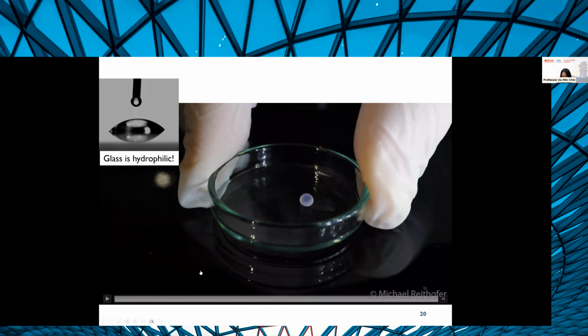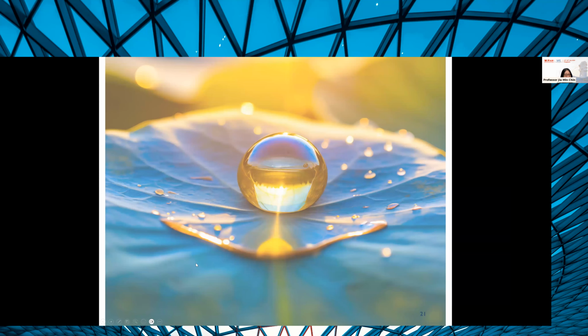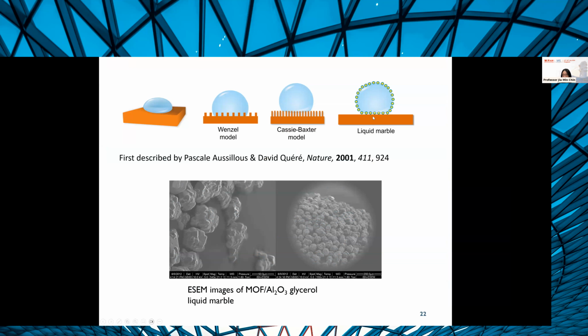And when we first saw this phenomenon, we were like, whoa, that is so cool. What is this? It's a little bit reminiscent of a water droplet on a lotus leaf, right? And it turns out that these are what are called liquid marbles. They were first described by Aussillous and Quéré in 2001. And this is a drawing to illustrate what's happening. In the Cassie-Baxter model for a superhydrophobic surface, you have a rough surface with asperities, and then you've got air pockets, and you have this liquid droplet sitting on top of the asperities and partially supported by these air pockets. In a liquid marble, instead of these asperities being attached to the substrate, your protrusions are attached to your liquid surface. And what happens is that if this liquid droplet rolls around, the particles roll around with it, and it thinks that no matter where it rolls, it's on a very repellent surface.